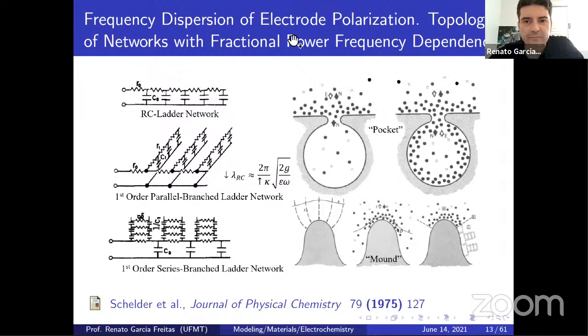Soon after, we have this paper of Schelder in 1975, who studied the network fractional power frequency dependence. Up to this time, we see that this is fractional, not fractal, it's the fractional power frequency dependence, because the researchers up to 1975 observed that the alpha values don't fit the impedance very well. If you take a look at the Nyquist impedance, isn't it? We don't have a semicircle. We call it a semicircle, but indeed it's a depressed semicircle.